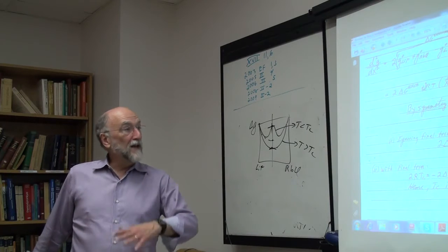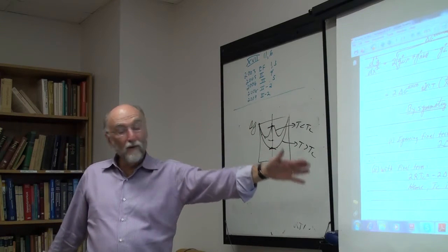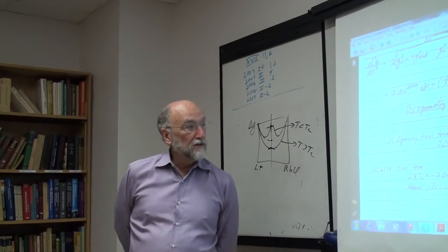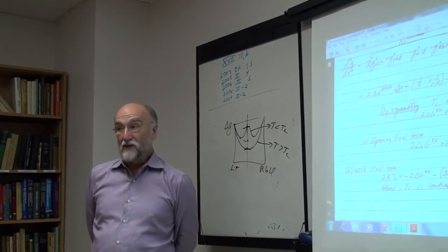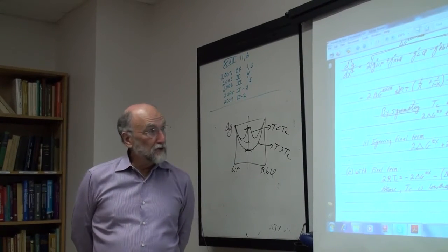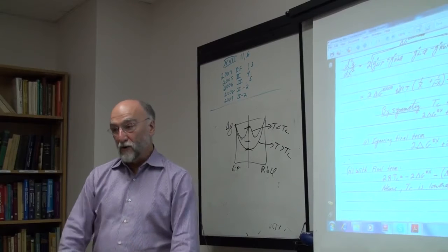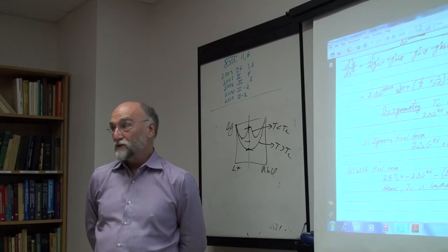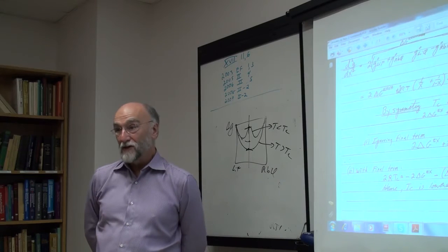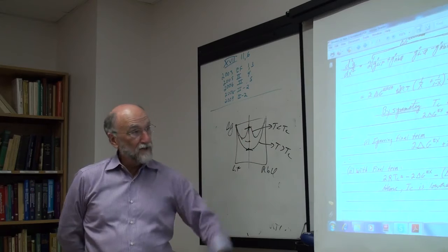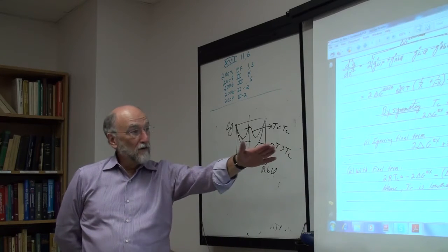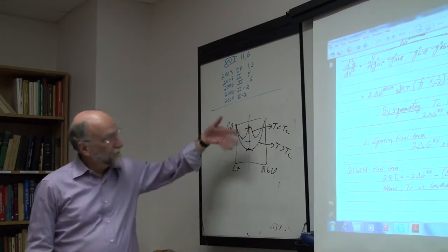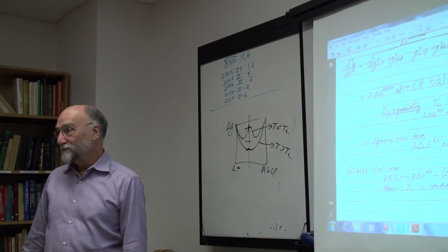Or the other way of looking at it is anytime you remove a constraint on your model, the constraint was at first, without that final term, the constraint is that it's a random mixture. Now you're saying it doesn't have to be a random mixture. So you remove a constraint, the liquid will always lower its free energy. Free energy with the removing constraint will always be lower than the free energy with the constraint, because the system always tries to lower its Gibbs energy. Give it another chance to do so, it does so. So removing the constraint, you lower the Gibbs energy of the system, so it'll surely make it more stable and lower the miscibility gap.